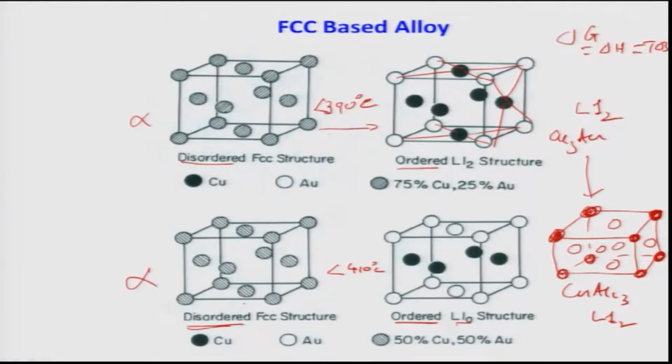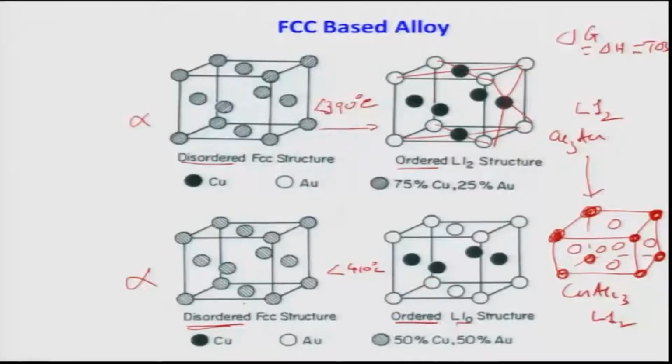We consider the 2 atoms in the face center positions in the unit cells, and if we draw a large number of unit cells, we can connect them and get a simple cubic structure that way. So, this is nothing but 4 simple cubic sublattices, 1 gold type and the other 3 copper type. That can always be done for any structure.